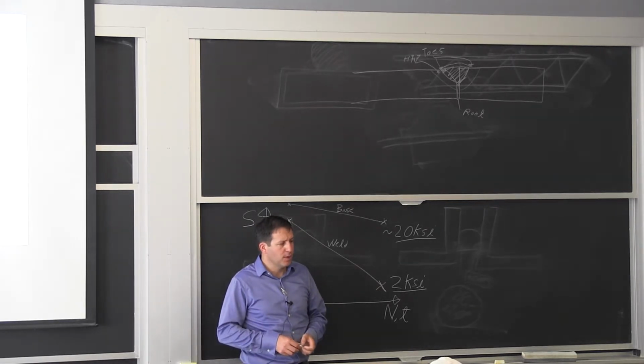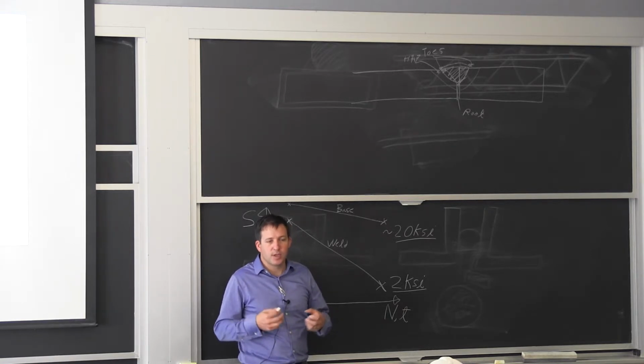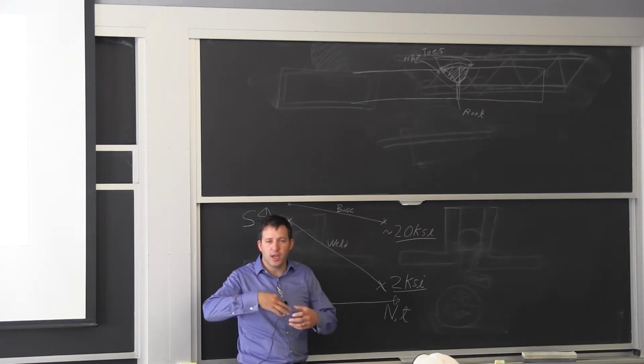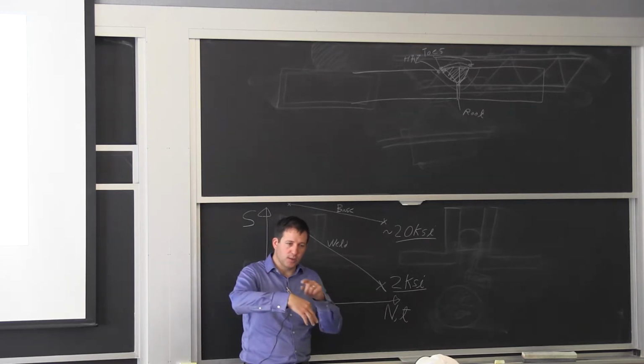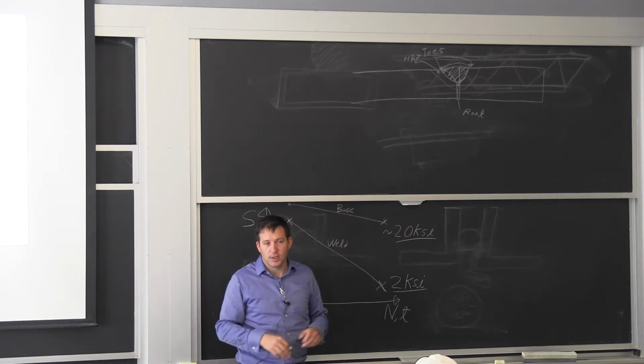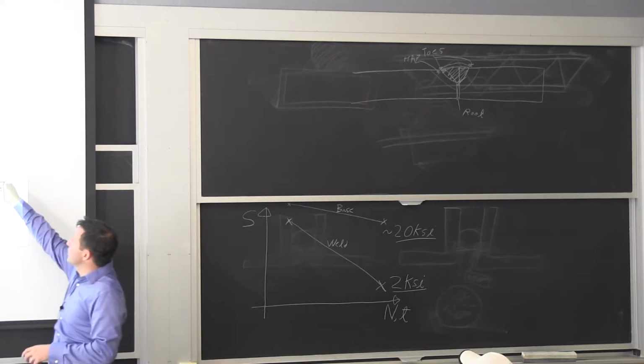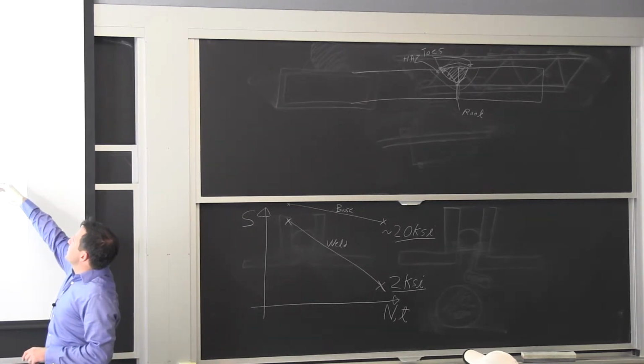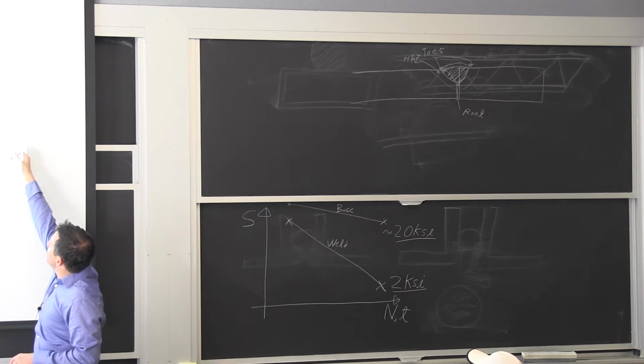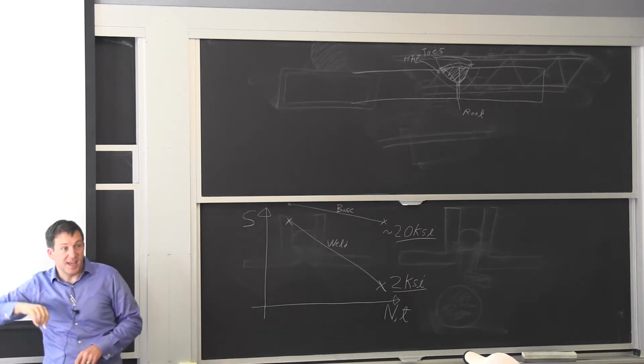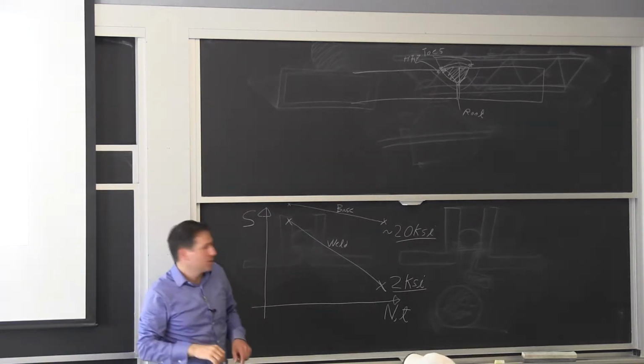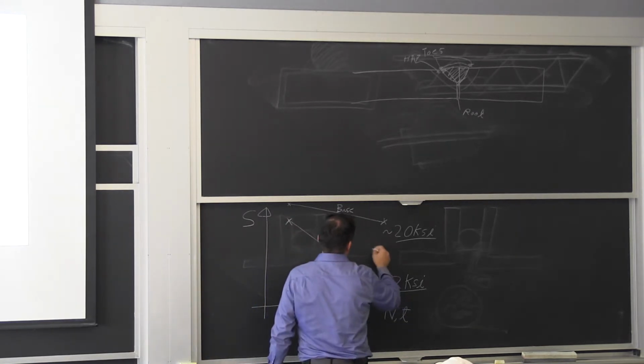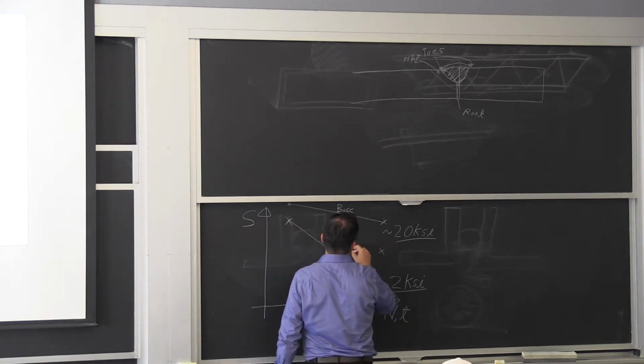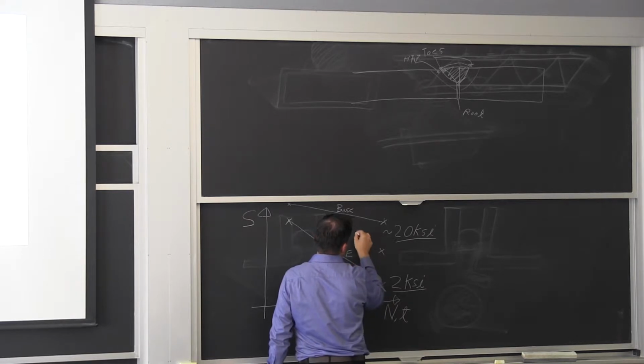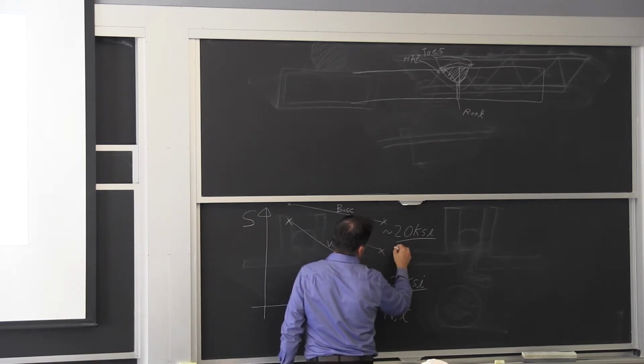If you remember, maybe I'll bring this on Wednesday, the gusset plate design is really where this all comes into play, when you notch a member and bring it in and you put the weld in shear, essentially. That's how you can start going from that 2 or 3 KSI all the way up to, say, you may be able to make a category C. Now all of a sudden you're at 10. So you can make a weld, I'll put another weld here. So that's the weld E, but the weld C will get you somewhere around 10 KSI.